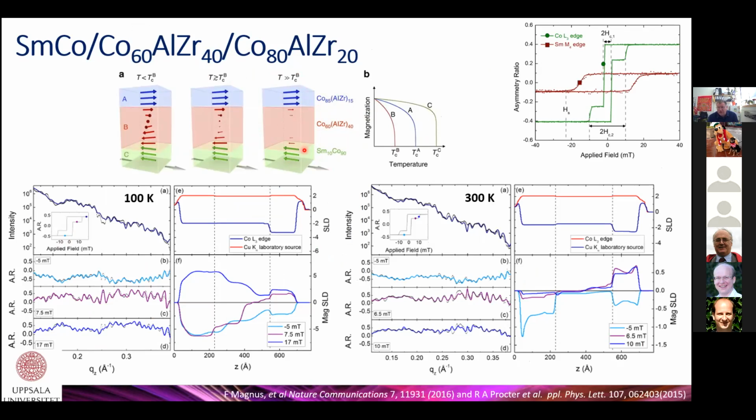So if you look at the magnetization, you'll find that the cobalt and the samarium seem to be completely decoupled, which is quite strange, bearing in mind there should be cobalt in this bottom layer. And we argue that's to do with percolation effects, essentially. So you've got this interesting magnetization behavior, which you can track out. There is some exchange bias in this system.